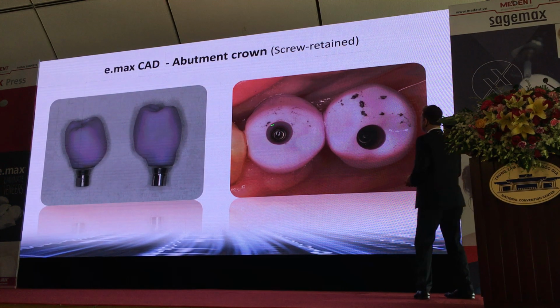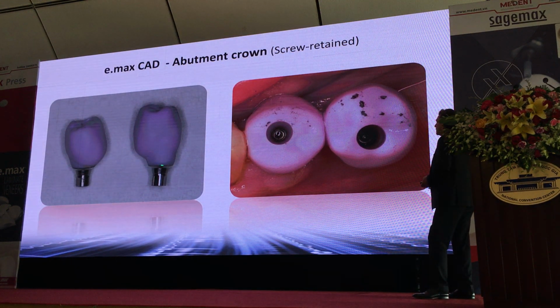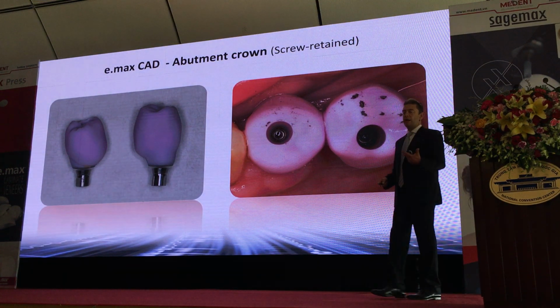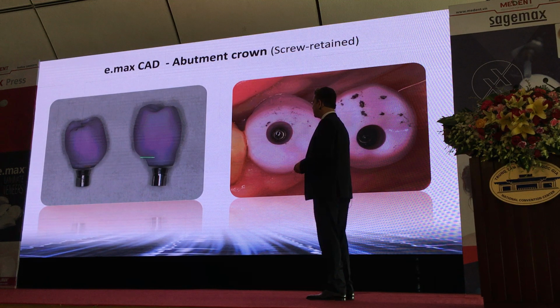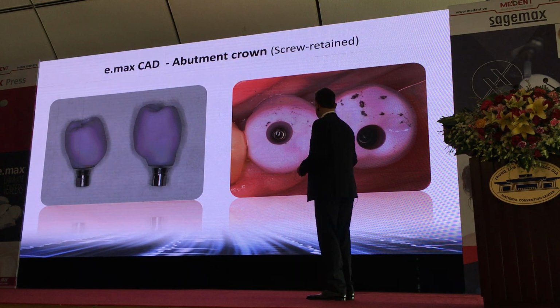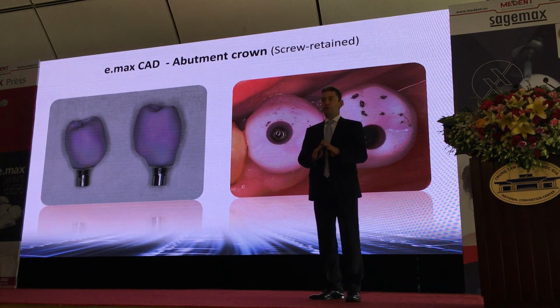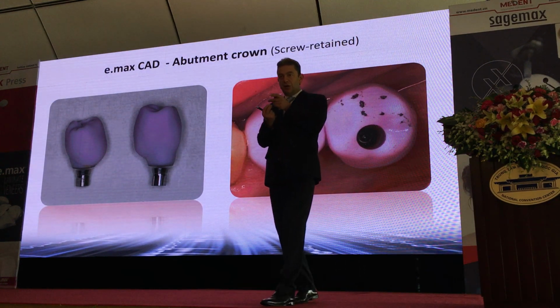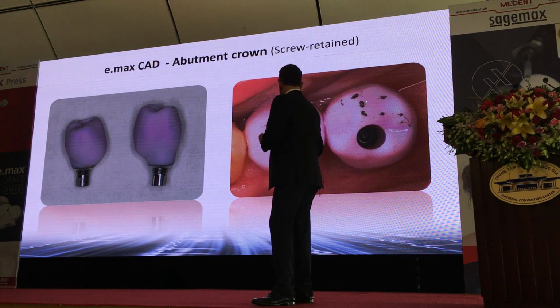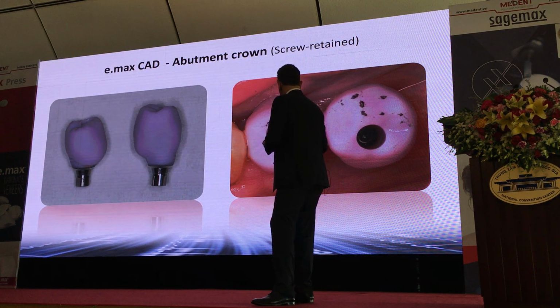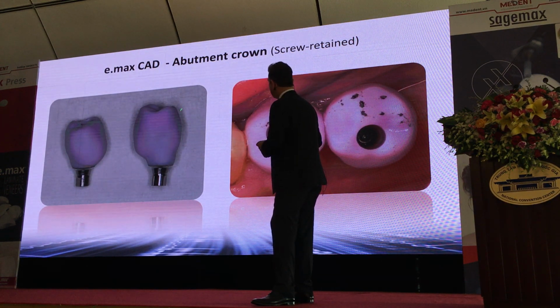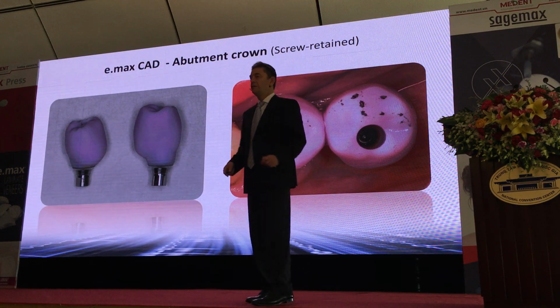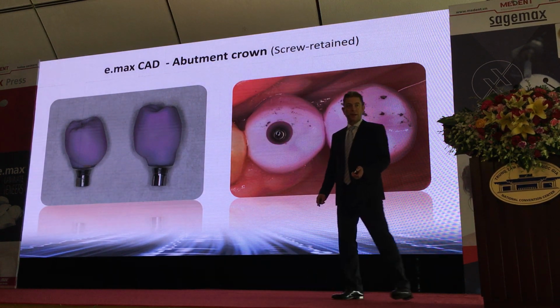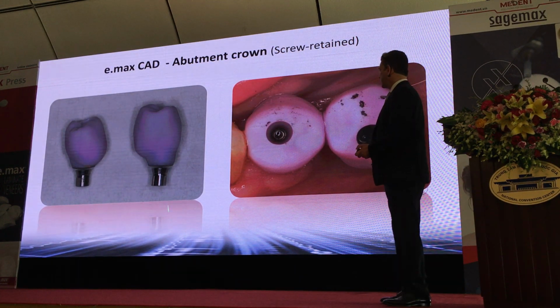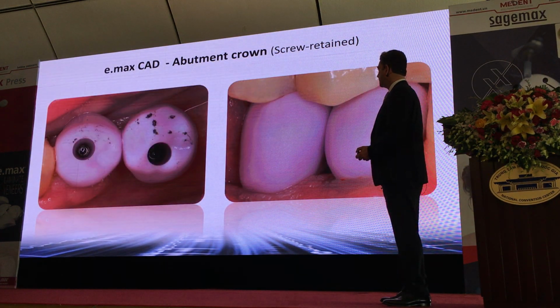Okay, so this, you can do a try-in. For example, for the try-in, you can use a little bit of silicone, like a light body or extra light body silicone, so that you can just try it in. So this one is not yet connected, okay? It's two separate pieces still, just with a little bit of silicone that you can try it in, to check the contact points and whether everything is okay. And only then we can go for crystallization in the furnace. And after that we can connect it together permanently.